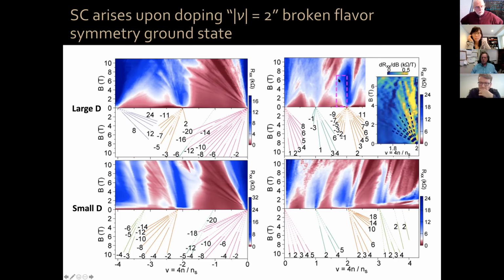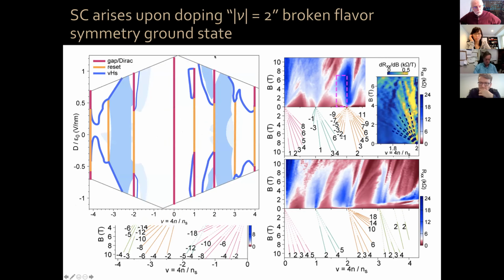Okay, so around nu equals 2, we have a fan diagram pointing inward, and what that is telling you is that in this region we have superconductivity, but the superconductivity that occurs is because we have a reset that has occurred where your Fermi level has been sent not to charge neutrality, but it's a strong reset to send your Fermi level under the charge neutrality point to the hole doping region.